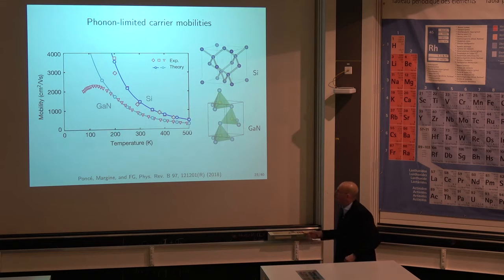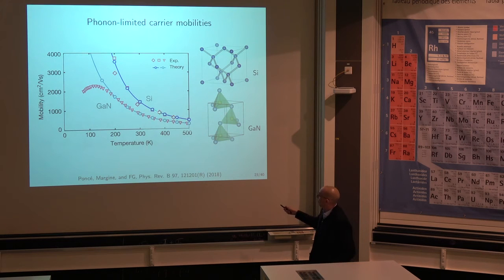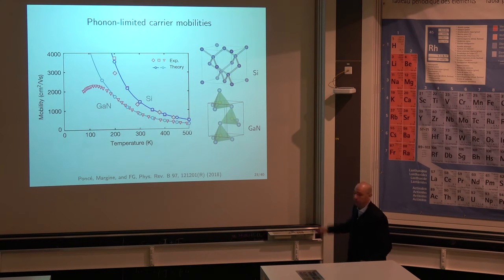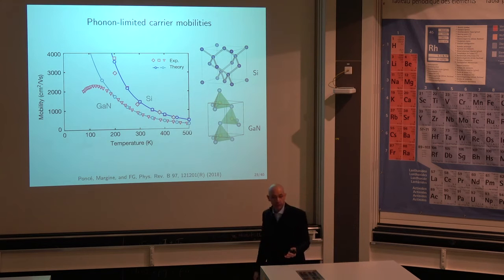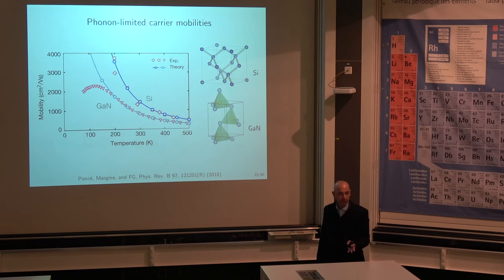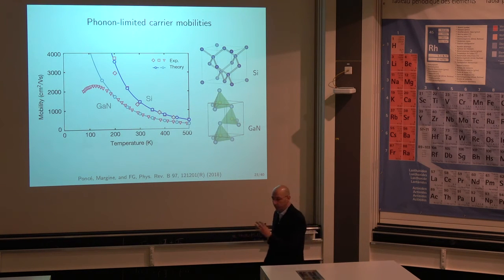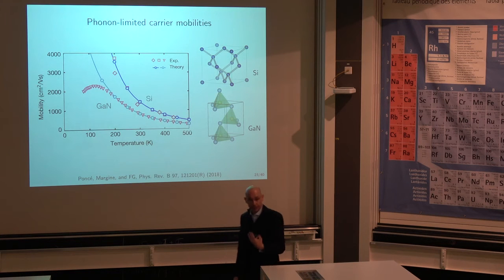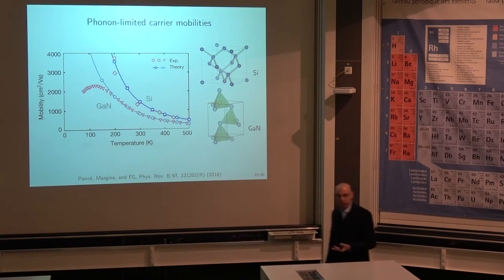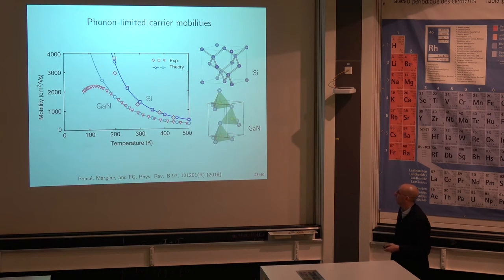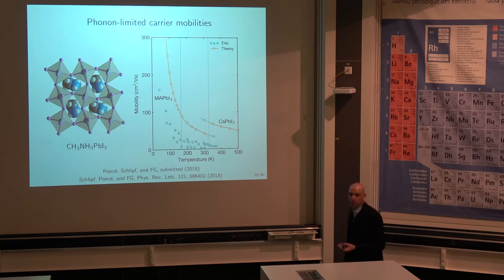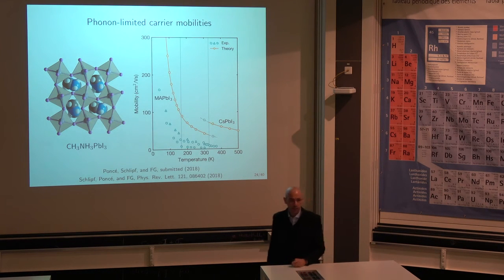So that's basically the mobility of silicon and gallium nitride as a function of temperature. So you can see basically the blue lines are our calculations, and basically the red things are the experiments. And you can see here that the agreement is pretty impressive, both for silicon and for gallium nitride. And I would like to emphasize again, there are no empirical parameters in these calculations. So this is basically a way to say that now we are finally at the point where we can predict mobilities. And this is quite important if you want to design new electronic devices, for example. Just to tell you that we don't do only systems with 2 or 3 atoms. We also did something a bit more challenging.